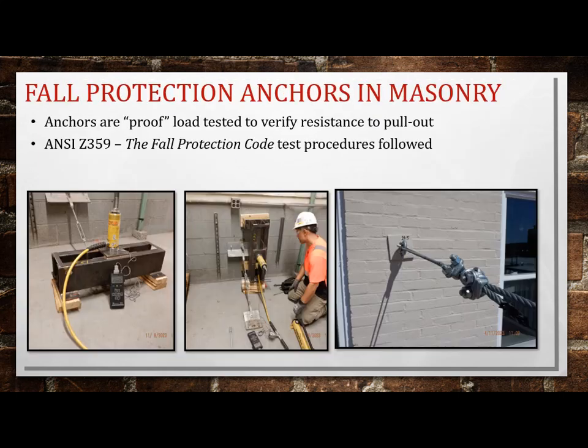failure. So this is us testing some fall protection anchors in masonry, and it's important that when we test these, if you look at the base of our testing apparatus, it's wide, because if you test right next to the anchor, you're supporting the substrate, and so you can't get that cone fracture if that should occur.